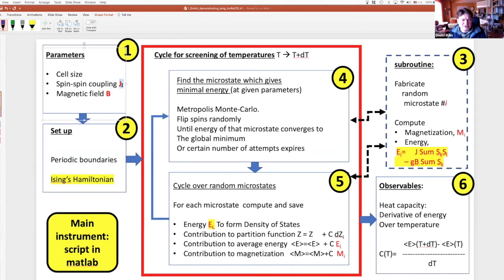values of spin-spin coupling. In the code, the value of spin-spin coupling means how the energy of two electrons localized in one ruthenium and another will change if you flip one spin compared to another. This parameter can be computed from, let's say, VASP by using non-collinear or spin polarized DFT with constraints.